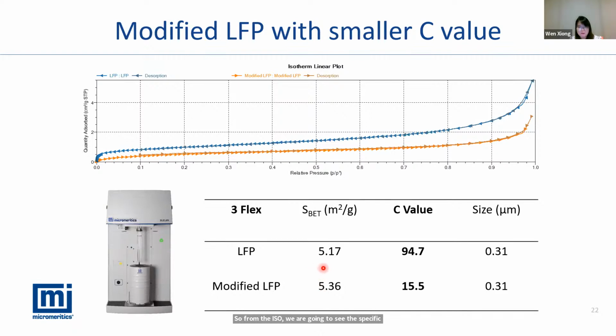slightly, from 5.17 to 5.36, but we focus on the C value change here. The C value changed dramatically, from 94.7 to 15.5. That means using our 3Flex, a very high performance instrument, we are able to use the nitrogen molecule to determine the tiny, very small surface modification on the surface.